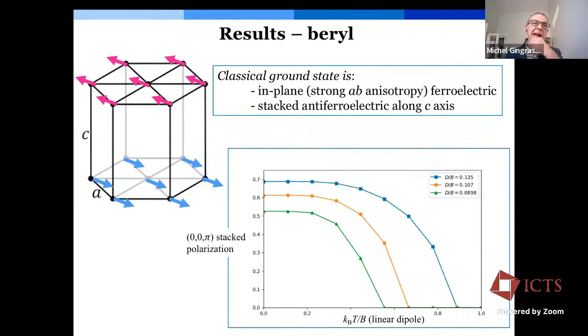Each hexagonal layer consists of dipoles which are polarized in a common direction, but from one hexagonal layer to the other, the relative orientation of the dipole flips by pi. But within a given plane, those dipoles are free to rotate. So there is a degeneracy that exists in the system where the dipoles essentially behave like XY rotors.